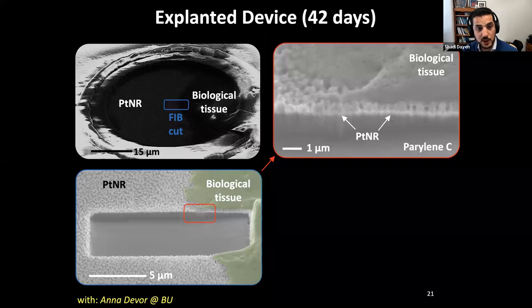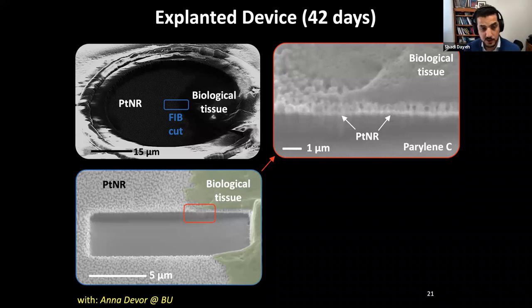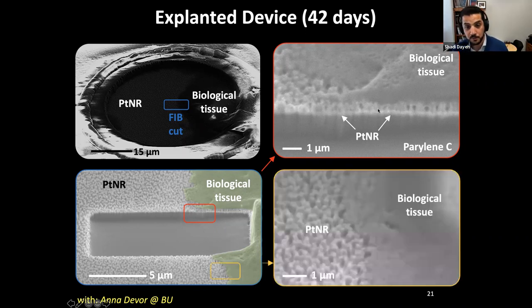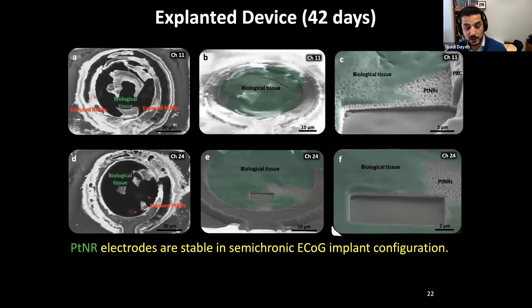The slides that are shown here relate to the stability of the electrodes in vivo. This was implanted in a mouse's brain for 42 days, explanted, and then we do FIB cut. And you can see that the density of the wires under the tissue and outside the tissue is the same. Basically, the wires are stable in vivo. Maybe this image can show things a little bit more clearly. You can see here wire distribution outside and inside are relatively the same. So we don't have wire breakage.